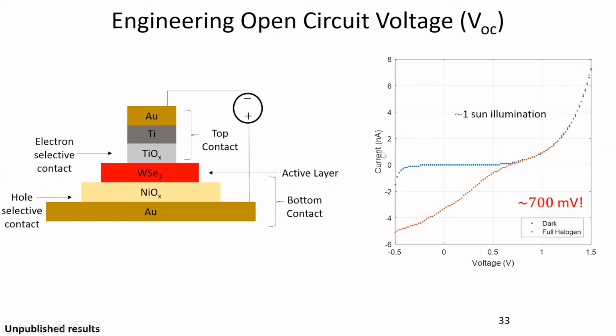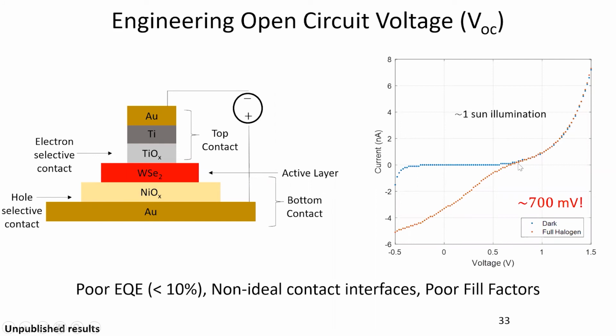But then if you look at the currents over here, the currents are terrible. This is because these transparent conducting contacts are quite resistive, and again the interface is not perfect, so they are leading to a lot of recombination. Further, if you look at this curve, there's an S-shape, which is a clear sign that there is some kind of Fermi level pinning going on at one of the contacts. We still haven't figured out where, but there is a lot of room for improvement in terms of contact engineering as well as interface engineering of the contact.